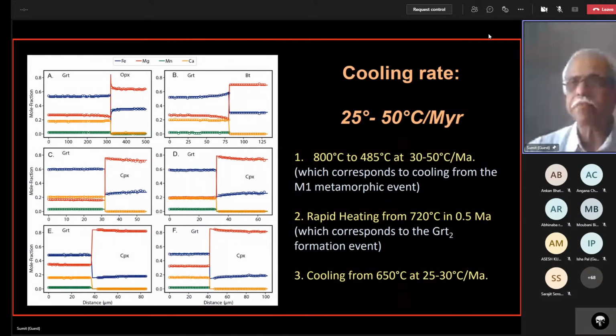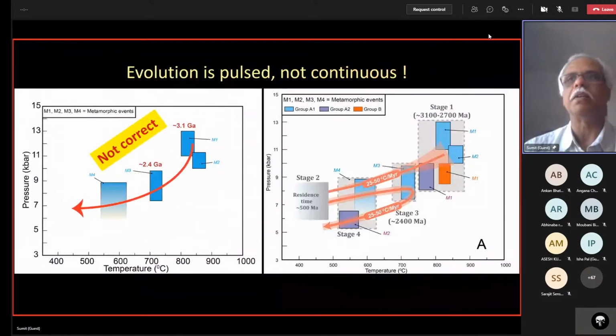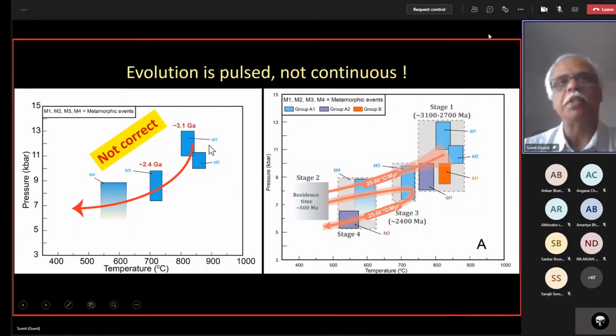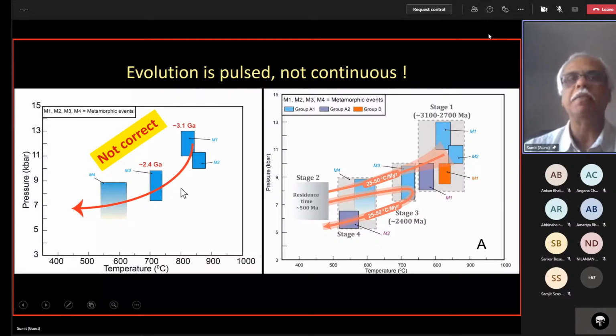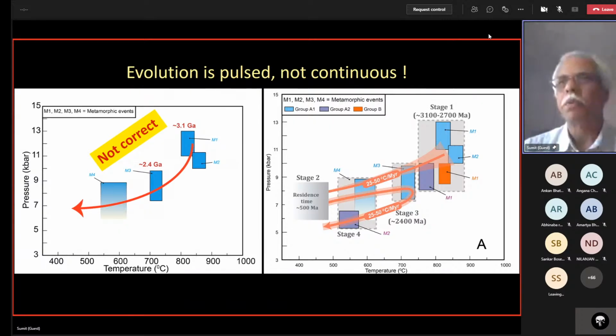Okay. Now, what does that do to my picture? So I had this picture initially that M1 at 3,100 million years, M2 at 2,400 million years, and then cooling down. Now, what that told me was that for the initial piece of this history, if I connect the dots with a smooth line, the history was one of very, very slow cooling. It's actually quite difficult to imagine how you can keep something hot for about 700 million years without doing something. Now, this cooling rate, this continuous tape recorder, tells us that it is actually something more complex.